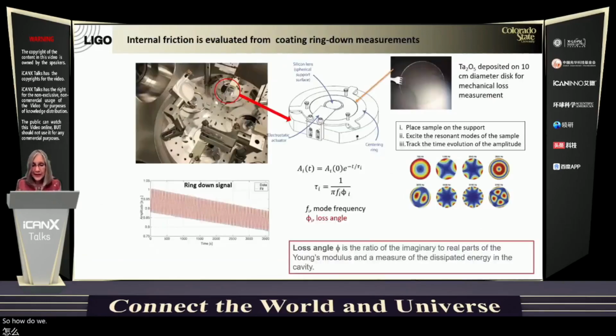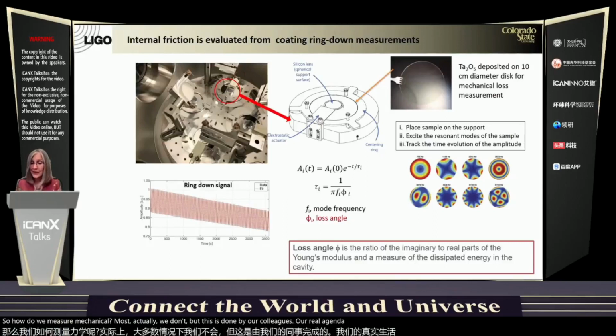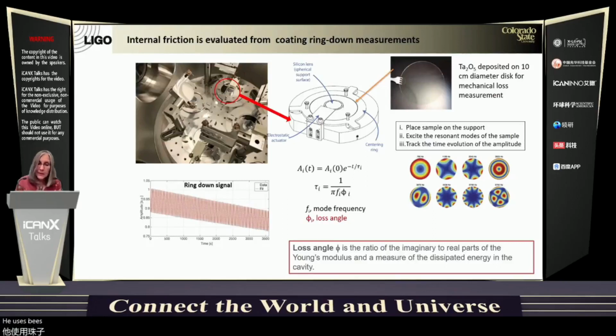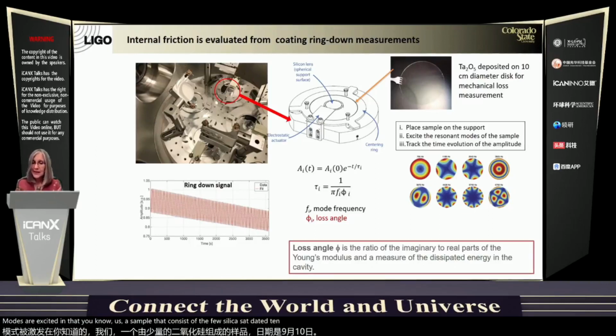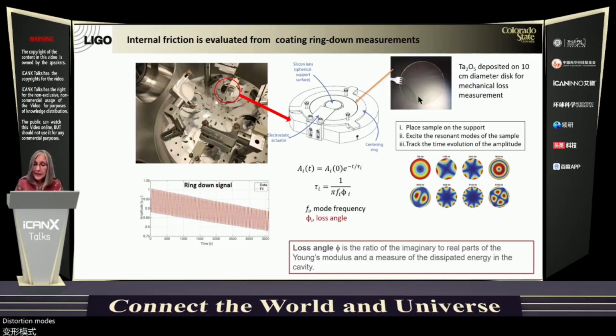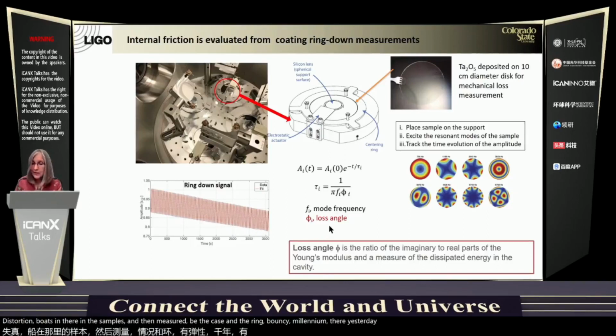So how do we measure mechanical loss? Actually, we don't, but this is done by our colleague Gabriele Vajente at LIGO Caltech. He uses the cavity ring down technique, in which different modes are excited in a sample that consists of a silica substrate of 10 centimeters in diameter, 1 millimeter thick, where we deposit the coatings. He excites the different distortion modes in these samples, and then measures the decay signal, the ring down signal, and from there extracts the mechanical loss angle.